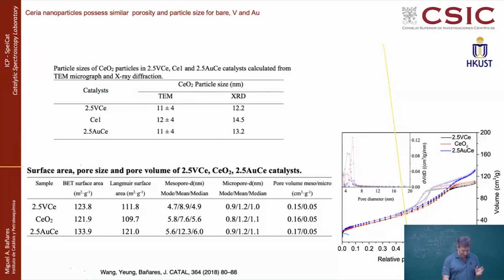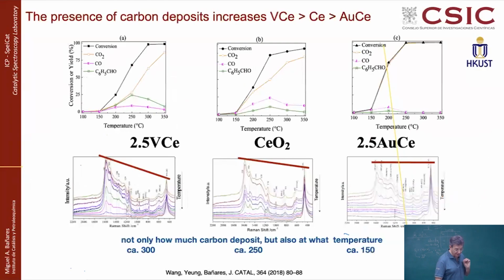So Qingyue prepared these materials, and the nice thing is that the crystal size is around 10 to 13 nanometer, either if you verify by microscopy or by X-ray diffraction. But also the nice thing is that this series she prepared had a very similar surface area, 120 to 130 square meters per gram. And in addition, the porosity was also very similar, which is important because then the only difference between these three samples is the composition. With a similar texture, with a similar particle size, you are obtaining something that will behave differently, because it is a bare ceria, it has vanadium, or it has gold.